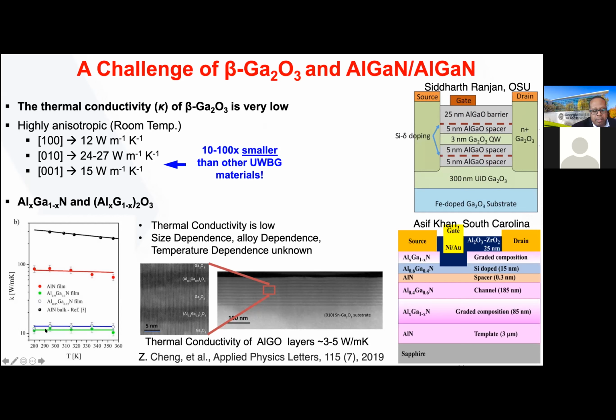So for AlGaN materials, the thermal conductivity is closer down here to about 10 watts per meter K, 10 to 15. What we have seen with AlGaO is that the few reports, the few numbers, can be as small as 3 to 5 watts per meter K. This is a measurement that was done by Z, where this is a superlattice structure with just a 10% AlGaO composition, and this superlattice stack right here was about 4.7 watts per meter K. So there's still a lot of unknowns in terms of what the thermal properties are, the temperature dependence, the thickness dependence, and the compositional dependence of these materials.